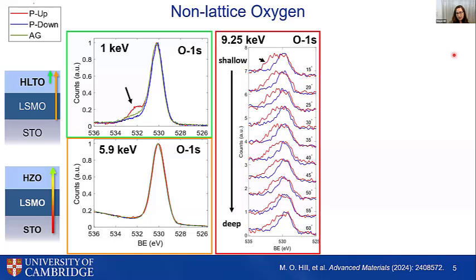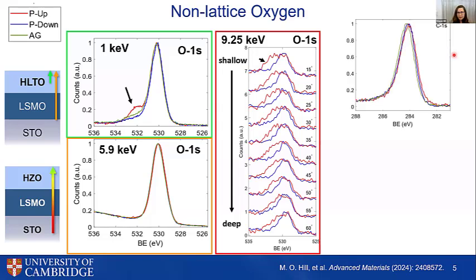If we look at the HZO, we can see the same peak arise, albeit at lower resolution, at 532 eV. And if we think about this briefly, many people would suspect that this peak comes from just the difference in atmospheric exposure of our sample. Maybe one sample was left out longer, or one sample was exposed to something slightly different before loading it into the UHV chamber. But in fact, these different regions of P up, P down, as grown were on the same sample, and they're just maybe 500 microns away from each other.